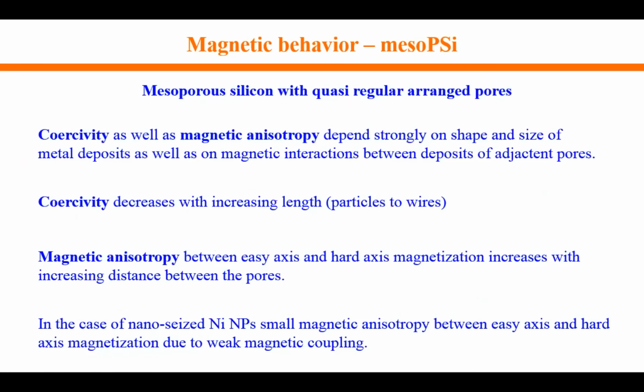So what we can say about mesoporous silicon is that the coercivity as well as the magnetic anisotropy strongly depend on the shape and the size of the metal deposits, as well as on the magnetic interactions between the deposits of adjacent pores. The coercivity decreases with increasing length, which means that the coercivity of particles is higher than of wires. The magnetic anisotropy between easy axis and hard axis magnetization increases with increasing distance between the pores due to less magnetic interaction. And in the case of nano-sized nickel particles, the magnetic anisotropy is small between easy axis and hard axis magnetization, and this is due to weak magnetic coupling.